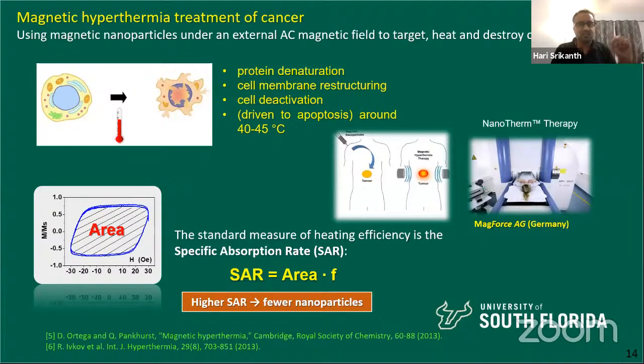So in other words, when you apply a high frequency, the magnetization is trying to follow it and it cannot, it goes out of phase. And because of that, you open up a hysteresis loop. But that's exactly what we want. That's why we need to apply high frequency, because we can maximize the area of the hysteresis loop. And remember, basic physics tells you that the area inside a hysteresis loop is nothing but dissipation. And dissipation here is in the form of heat. Power loss is in the form of heat. And that's how we generate heat, okay?